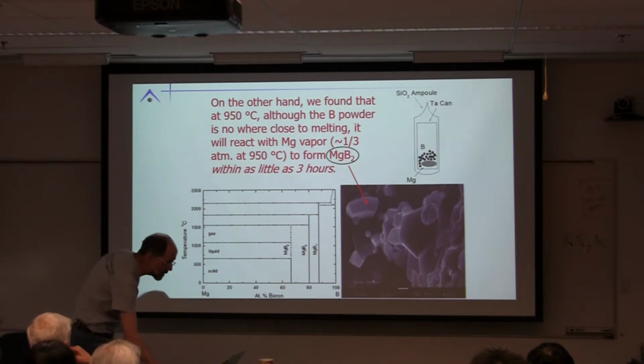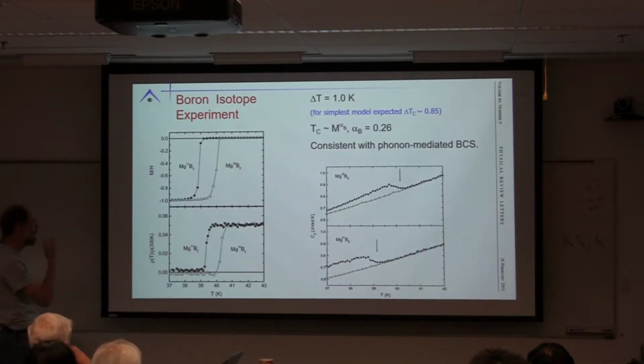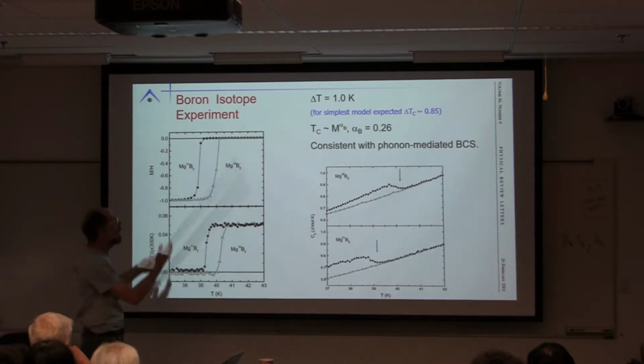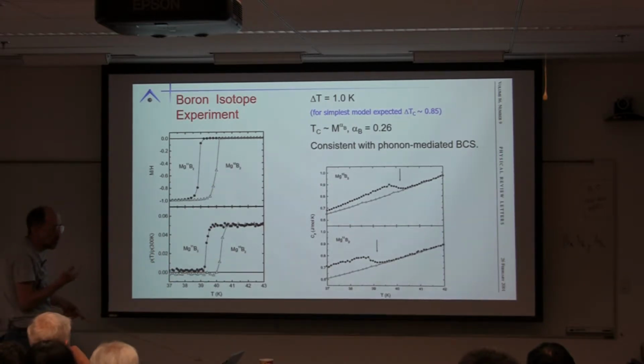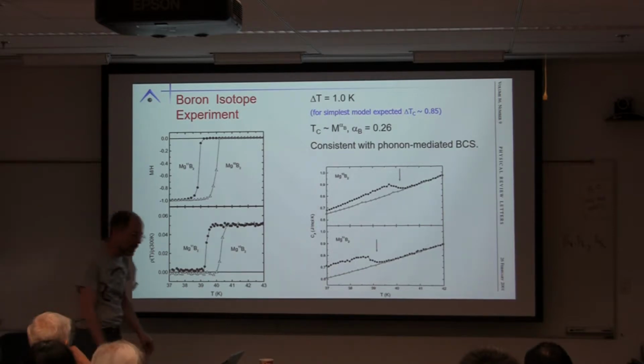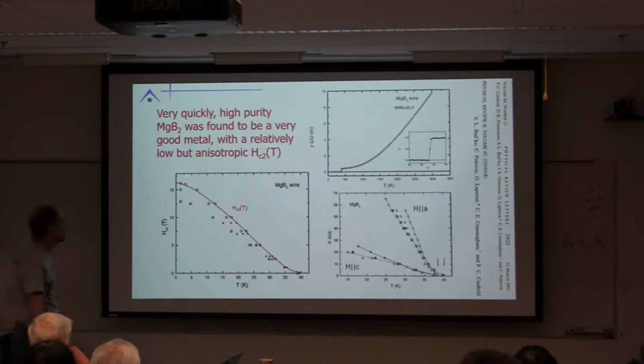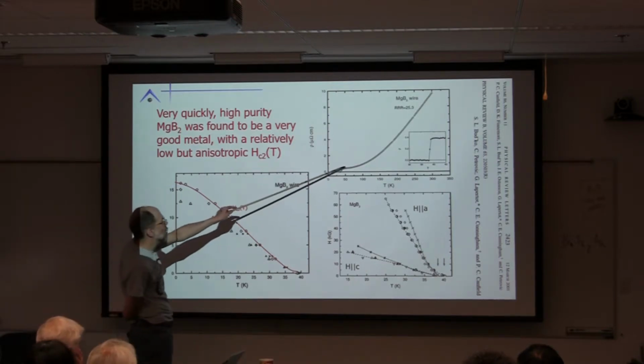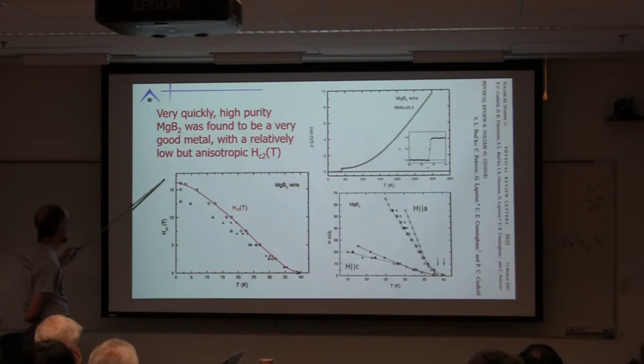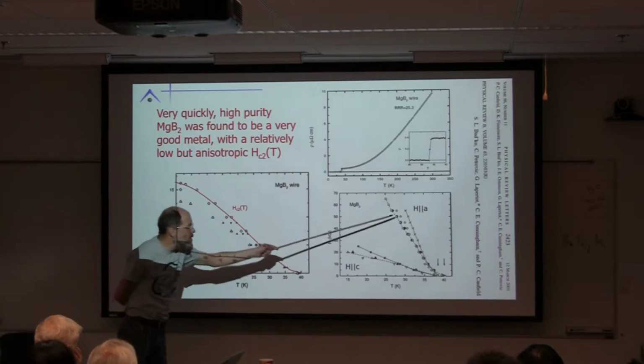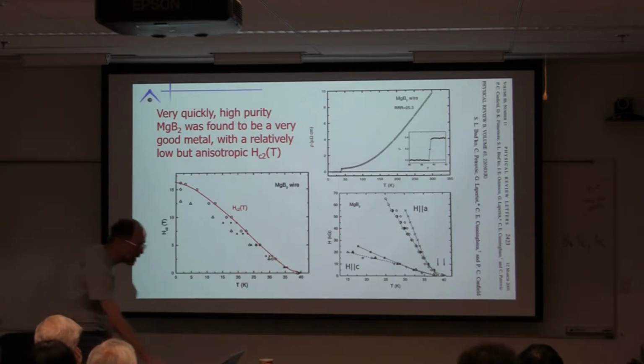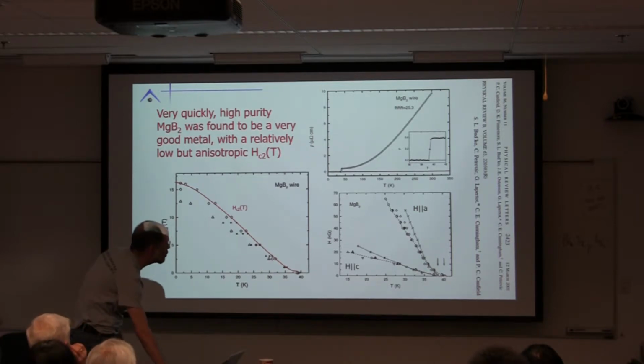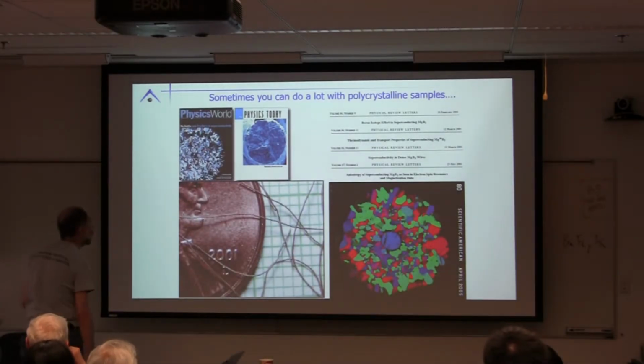Okay? Now, what that meant is, since we had isotopic boron on hand, we could immediately make isotopically pure MgB2 and see a 1 Kelvin isotope shift in magnetization and resistivity and specific heat. And this immediately made this clear to us and the community that this was a phonon-mediated superconductor. Okay? We could also, of course, characterize the basic properties. It's a fantastic metal. It has a moderately high Hc2, and we could even infer a relatively large anisotropy in the pure compound. And MgB2 for us, and for all of you too, should be a lesson, which is sometimes you can do a lot with polycrystalline samples.